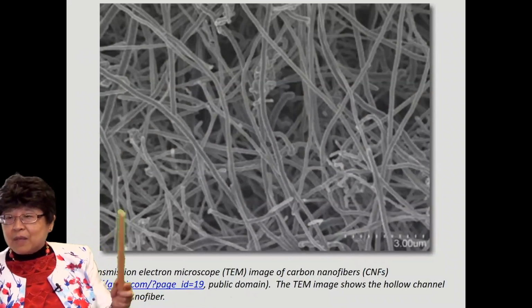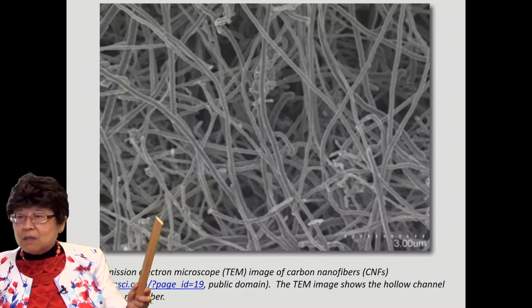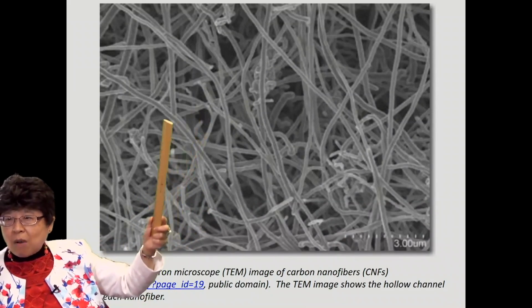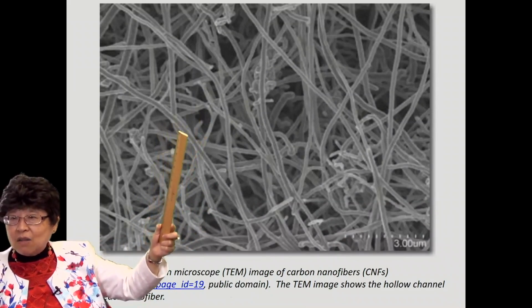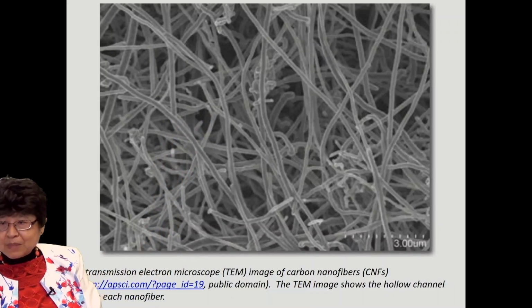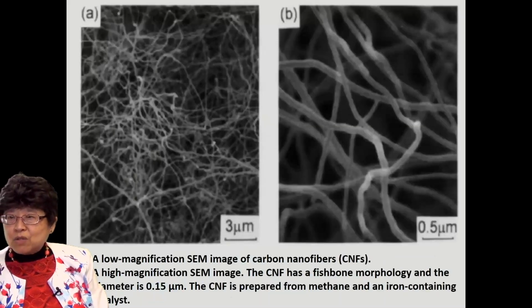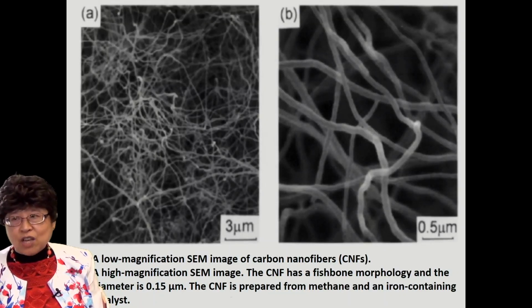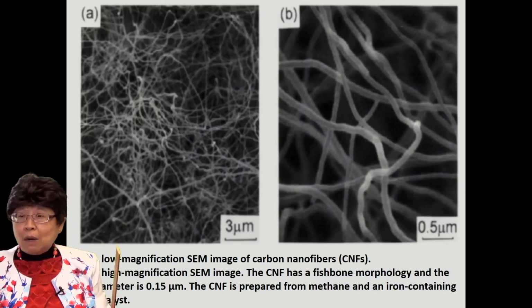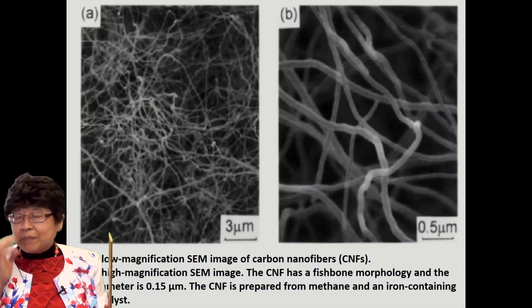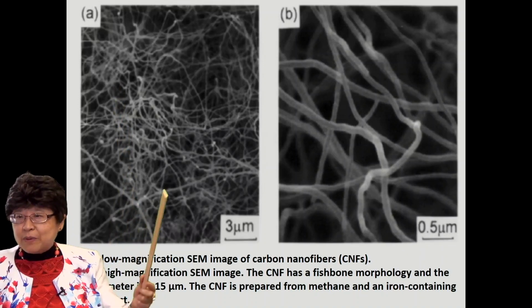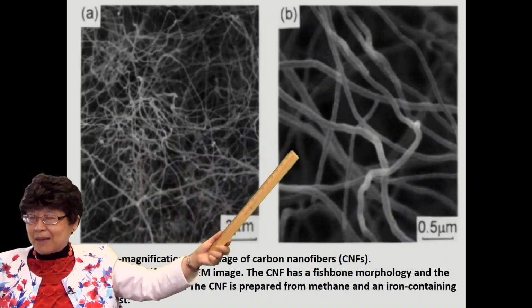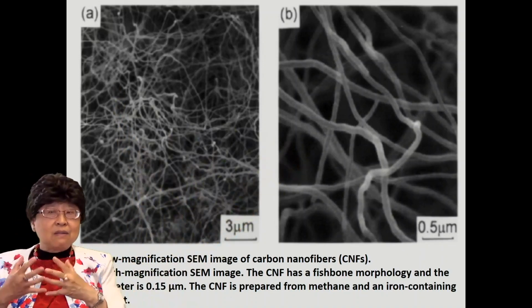This is a microscope picture showing the carbon nanofiber, and you can see a hollow channel in the middle, a TEM microscope view. But if you use SEM instead of TEM, then you cannot see the channel inside, because the SEM is just a reflective mode of operation. But you can see the nanofibers, low mag and high mag. Note that they are intertwined.